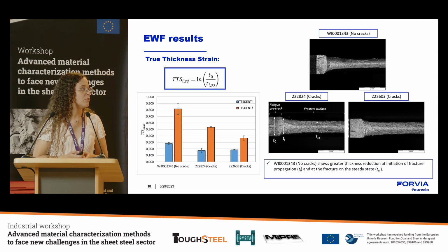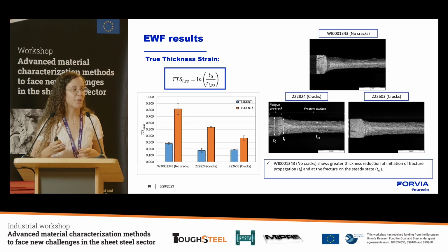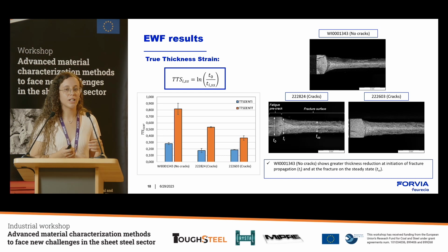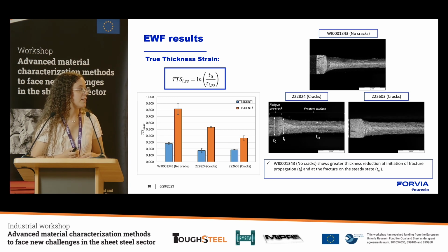Finally, we also performed these measurements of the true thickness strain, as we already saw before with the SSAB case study, that the correlation between the essential work of fracture values and these measurements was good. In this case, we can see also that the correlation with fracture toughness is similar for the three materials. The one presenting no cracks in the forming presents the highest true thickness strain values.